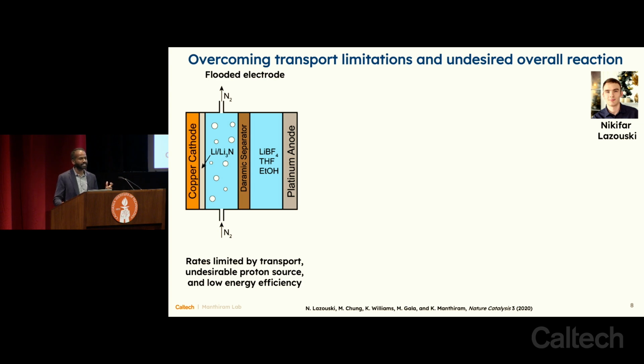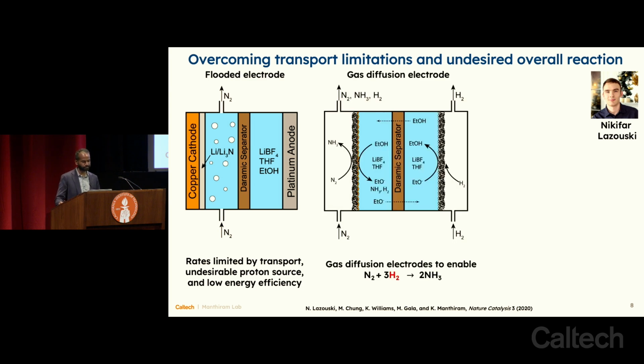What we found is that it is this journey of nitrogen from the bubble to the surface of the electrode that's limiting. It's not actually the reaction, this breaking of the nitrogen triple bond, that's the hard step. It is the physical movement, or transport, of nitrogen gas from the bubble to the surface of the electrode that was the step limiting the rate of this reaction. And so that's really the problem that we set out to solve at the very beginning.